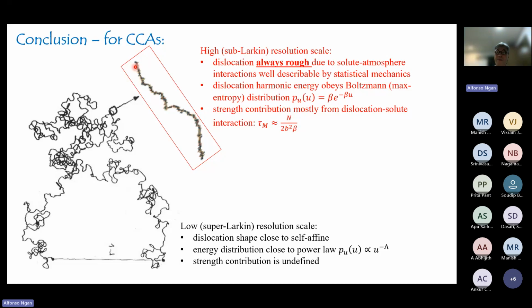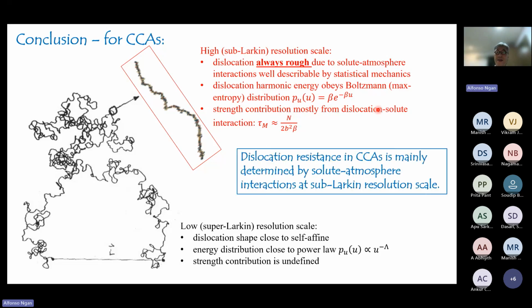And then the harmonic energies, if you do harmonic analysis on the wavy shape of the dislocation, the harmonic energies would obey the Boltzmann distribution. And the strength contribution basically is related to this term, where the most important factor here is the beta. 1 over beta would be the mean energy of the harmonic, of the Boltzmann distribution. And dislocation resistance in the case of CCAs is mainly dominated by this regime, by the sub-Larkin regime. So with that, I would like to stop. Thank you for your attention.